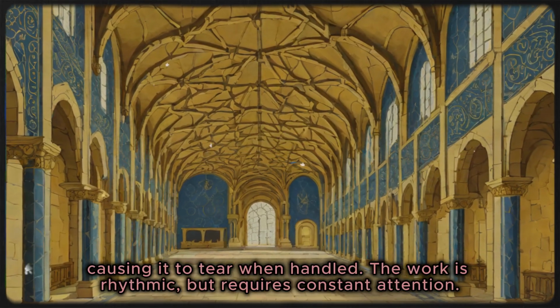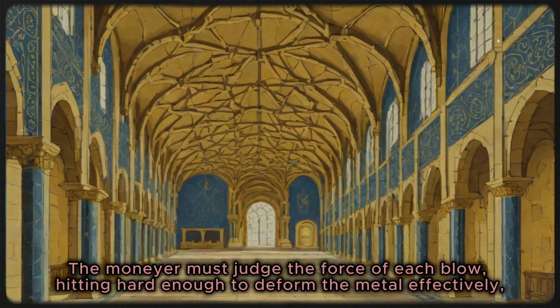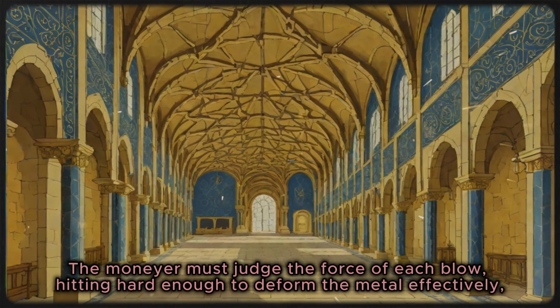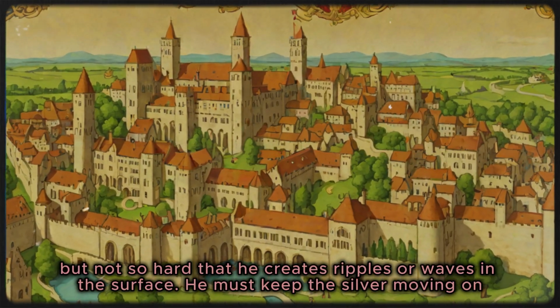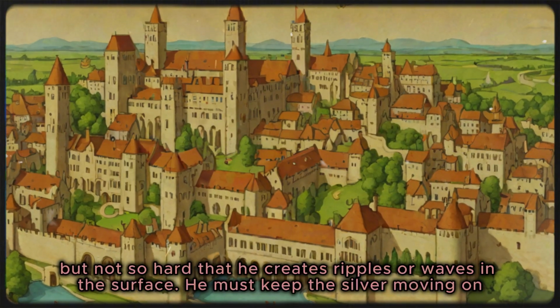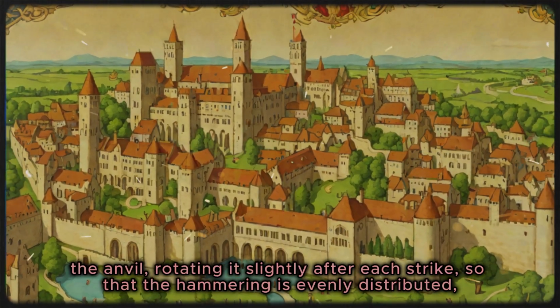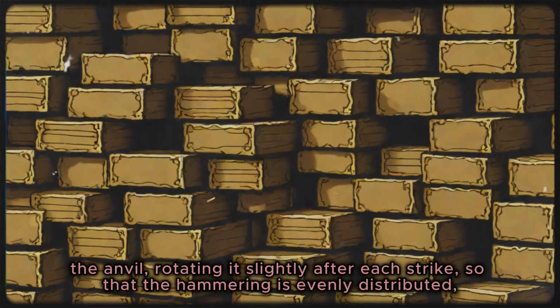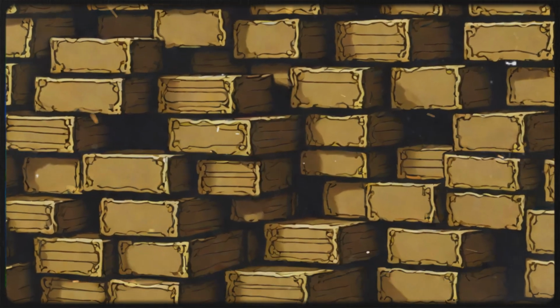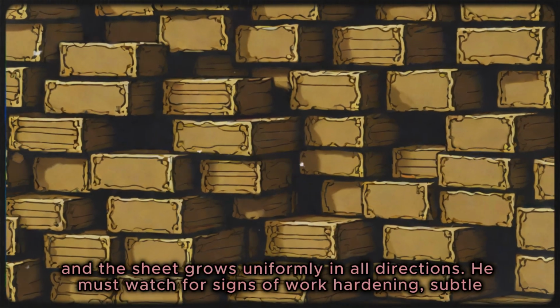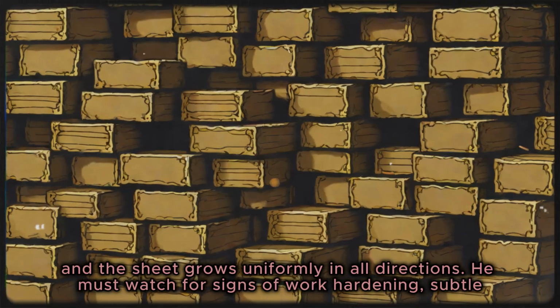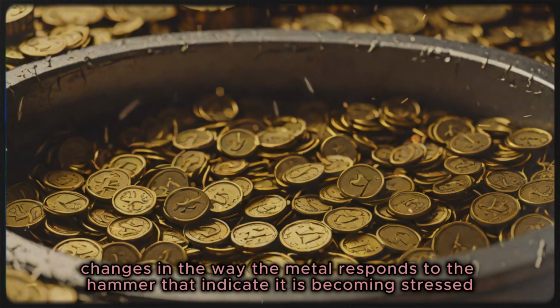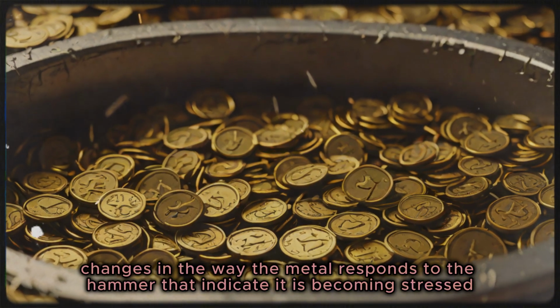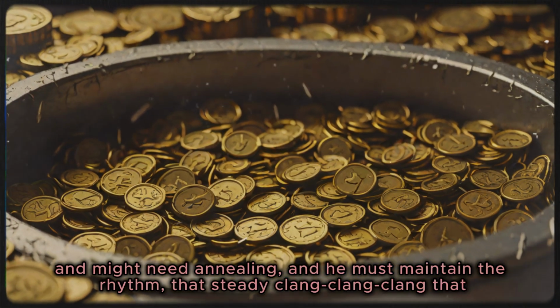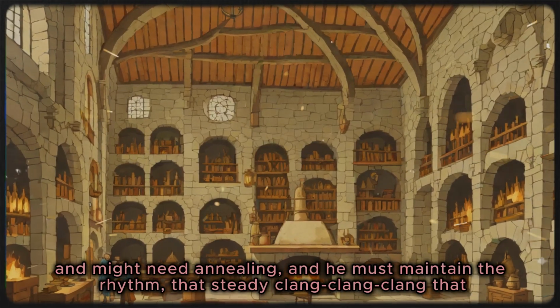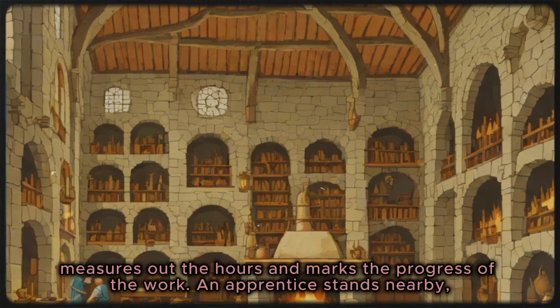The work is rhythmic, but requires constant attention. The moneyer must judge the force of each blow, hitting hard enough to deform the metal effectively, but not so hard that he creates ripples or waves in the surface. He must keep the silver moving on the anvil, rotating it slightly after each strike so that the hammering is evenly distributed and the sheet grows uniformly in all directions. He must watch for signs of work hardening, subtle changes in the way the metal responds to the hammer that indicate it is becoming stressed and might need annealing. And he must maintain the rhythm, that steady clang-clang-clang that measures out the hours and marks the progress of the work.